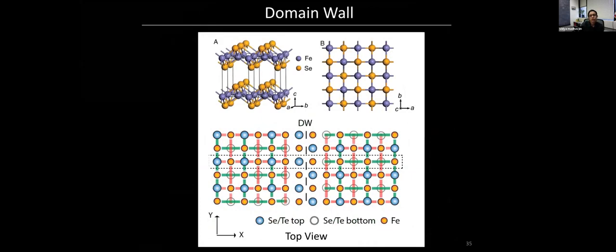So here's the idea. This is the top view on one side of the domain wall. These are the top selenium atoms. And then on the other side of the domain wall, the crystal has simply flipped over. So then what you expect to see is a half unit cell shift of the top atoms. These are the top atoms here, and these are the top atoms here. This is the domain wall. So you expect to see a half unit cell shift. And if you can find such a domain wall, then at least theoretically, you have all the ingredients necessary to